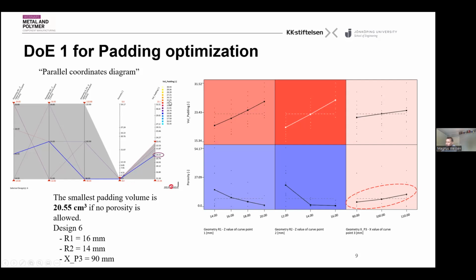In this case, this is the volume of my padding material, which is now something like 20. And that is the best solution, the lowest volume and still getting 0 porosity. So now I have to say, okay, I'm quite happy. I have a more robust process. I don't get any problems at any time, even for the worst parameter settings in the foundry.